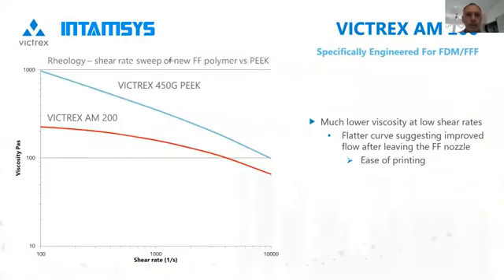When we take another look at the rheology graph of AM200 here in red compared to the PEEK from before, we see from the red line of AM200 that the initial viscosity is much lower than the blue line of the PEEK. PEEK would sit somewhere in between these two. AM200 is less viscous at low shear rates, meaning that good flow is possible through the nozzle at the shear rates that we commonly experience in filament fusion. And this is generally reflected by their easier printing at these lower temperatures.